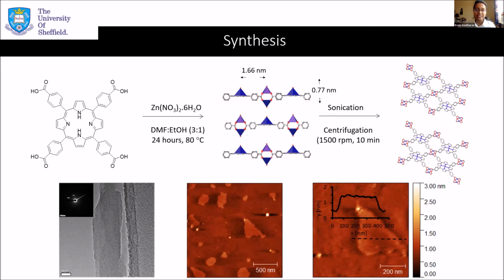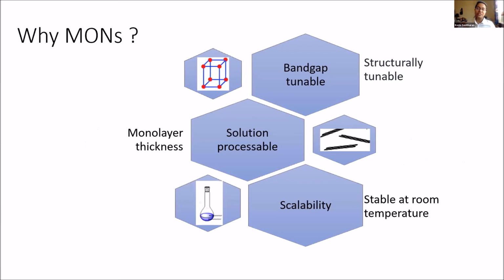Microscopic investigations show that these materials approach monolayer thickness and are about 100 to 500 nanometers in lateral dimension. So why MONs? These are an emerging class of 2D materials, and what sets them apart from other 2D materials like graphene and transition metal dichalcogenides is that their band gap is structurally tunable, not layer dependent. So the band gap arises from the organic linker that is being used to form these structures. They are also far more easily solution processable, approach monolayer thickness, can be easily scaled, and are also stable at room temperature.